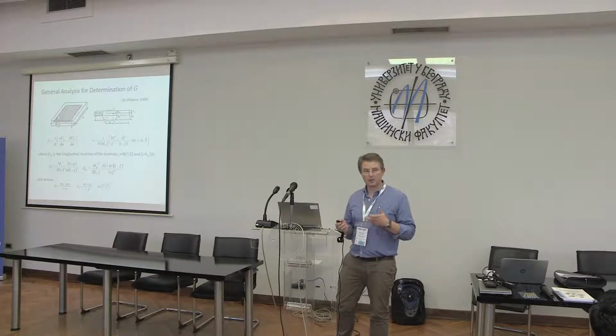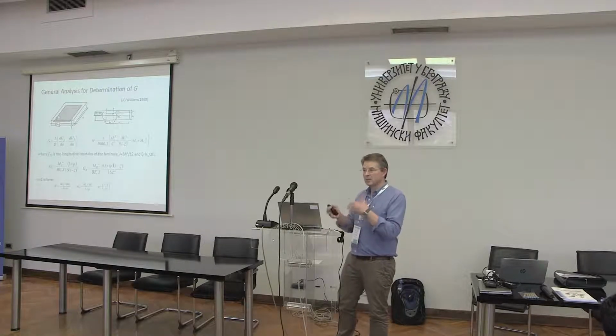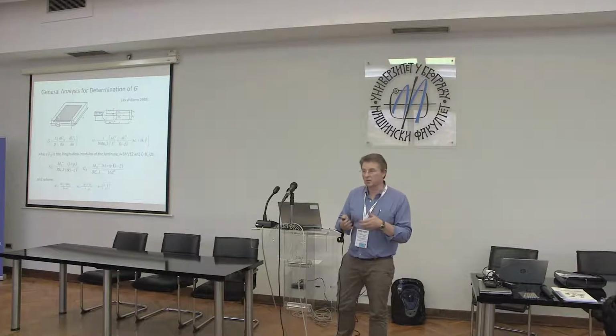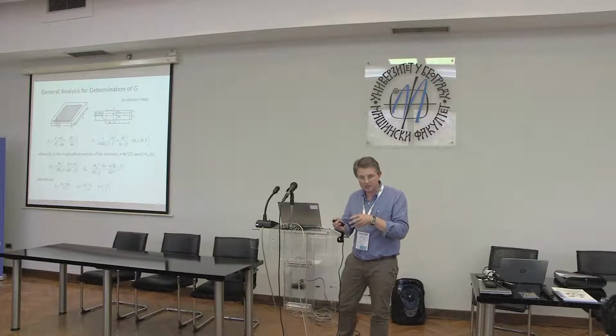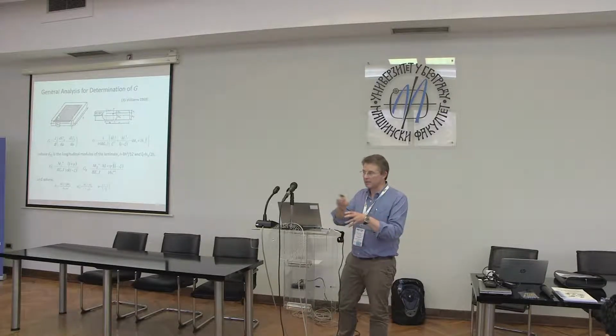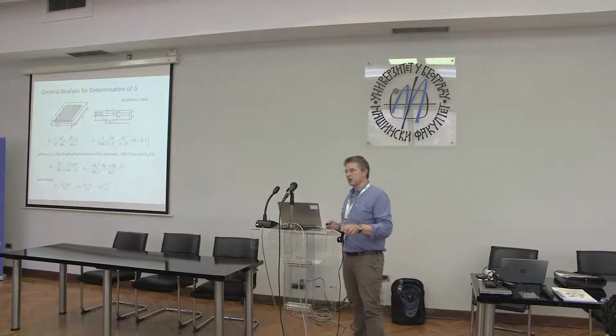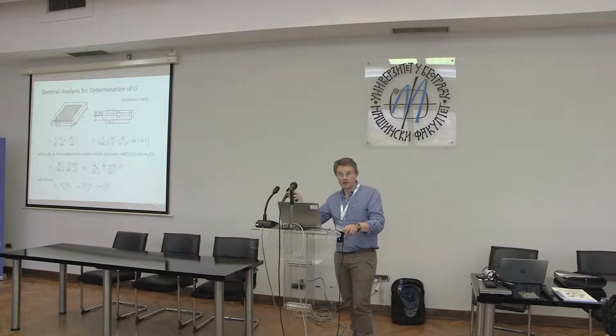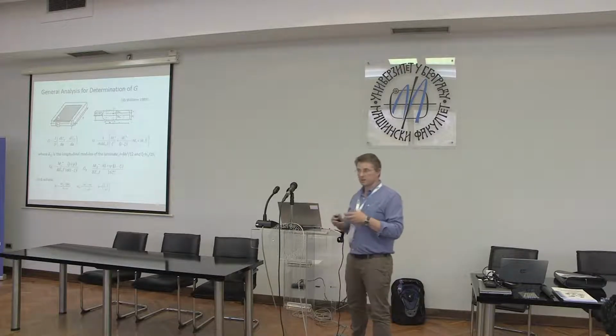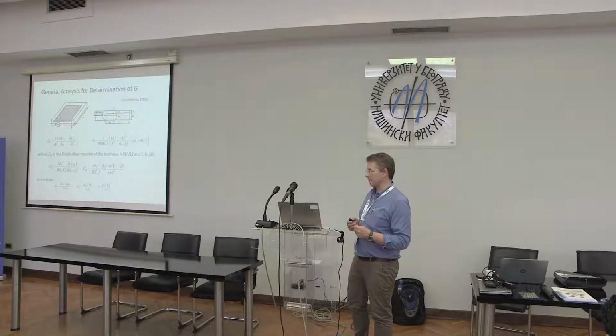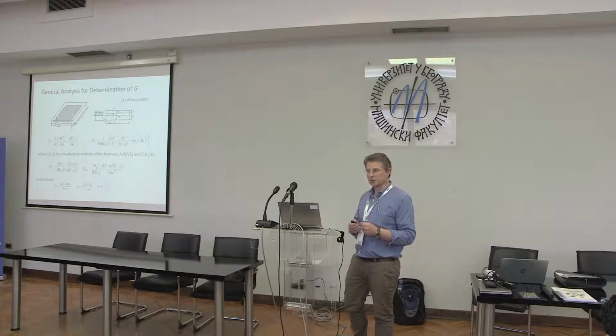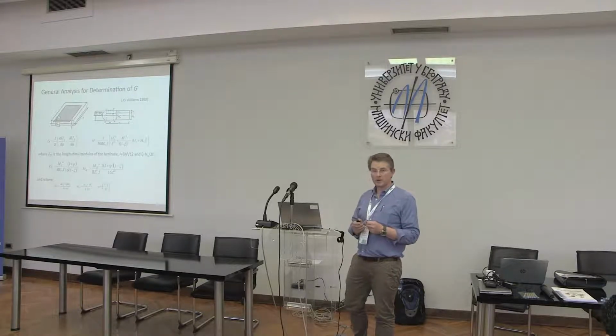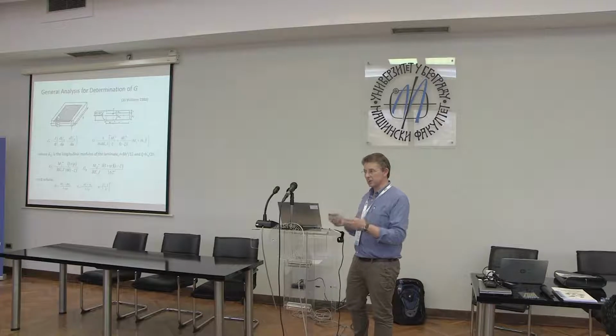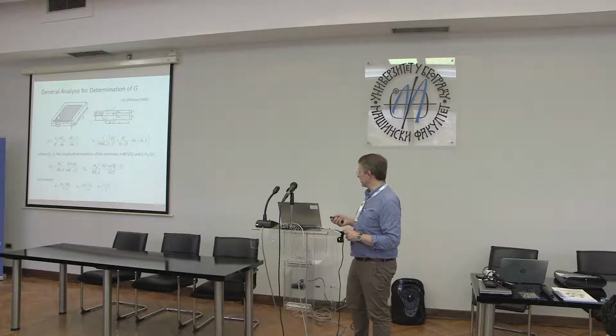And that was quite encouraging because obviously many of the analyses look at the details of what's happening at the crack tip. So you get into the K field and you get into the size of that and the specific stress displacement profile, stress crack length profile at the crack tip, and you build into lots of complexity. So what was quite appealing about this technique, this global analysis, was you simply needed to know what was happening away from the crack, and you determine the global energy release rates.